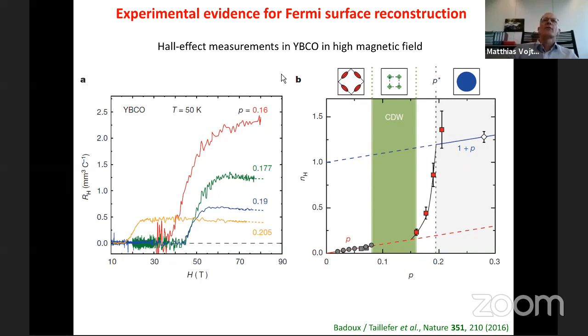These are measurements of the Hall effect in a particular cuprate superconductor in high magnetic fields. And from the Hall constant, you can deduce the carrier density, and this is what has been done. So in the left-hand plot, you see the Hall effect itself, and you can extrapolate the signal at elevated fields to zero field, and then you can come up with a Hall number, and this gives you the carrier density. And this is shown on the right-hand side as a function of doping. Doping is now called P, previously it was X.